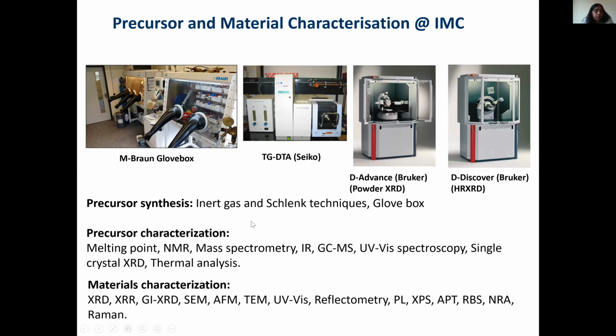And when we deposit the films, then we analyze in terms of structure, X-ray diffraction, microscopy, for example, the morphology, the topology, looking into the interface, looking into the optical properties, composition, photoluminescence spectroscopy, or atom probe tomography. This is one of the new techniques to look into the composition as well as the distribution of the atoms in a material system, and also Raman spectroscopy for characterizing the films.